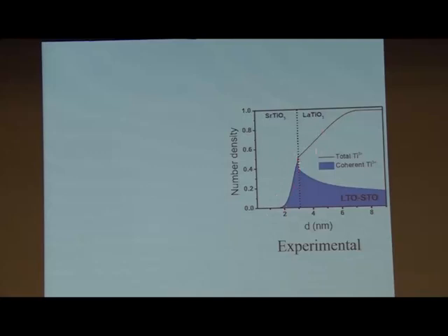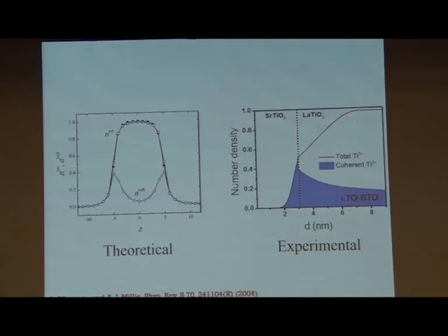But when you get in here, which is the Mott-Hubbard insulator originally, now doped metal, strongly correlated metal, its correlation-induced feature is very high. Only this part is the coherent feature. And the corresponding calculated result, because we need to look at only that, you can see has exactly similar behavior. You have this peak and going down, this peak and going down, and the total number of electrons going up like that.